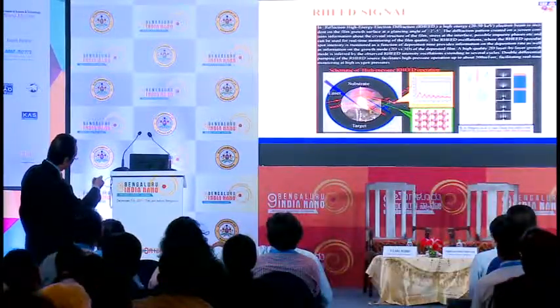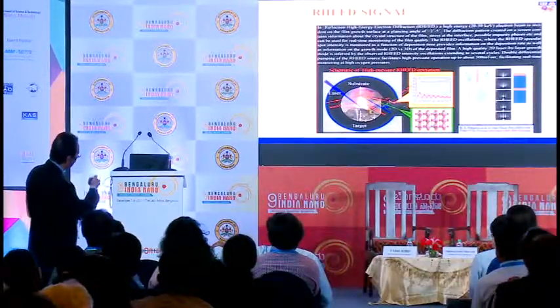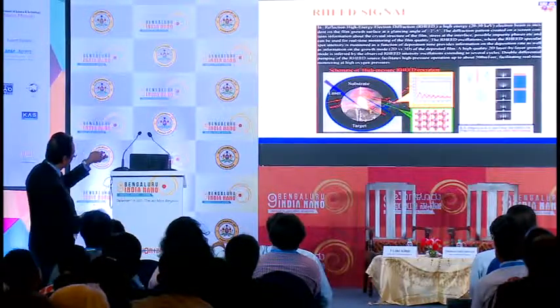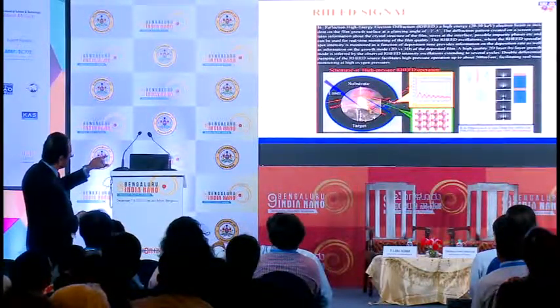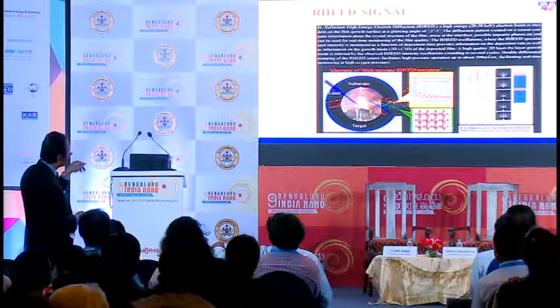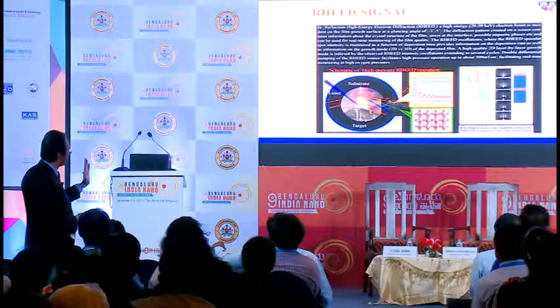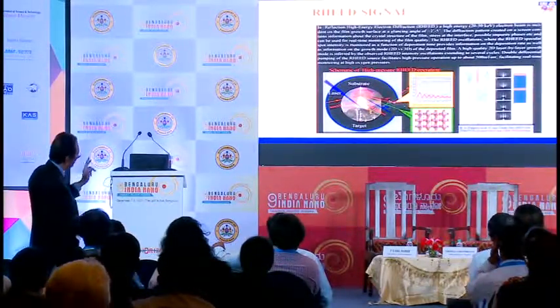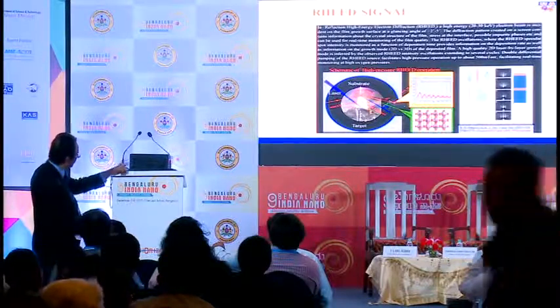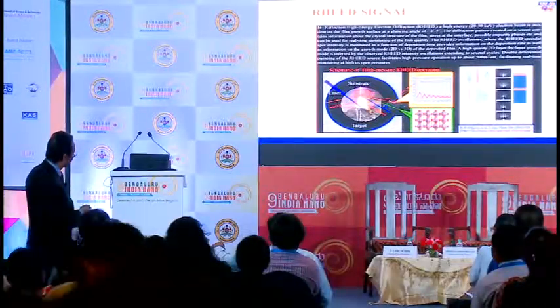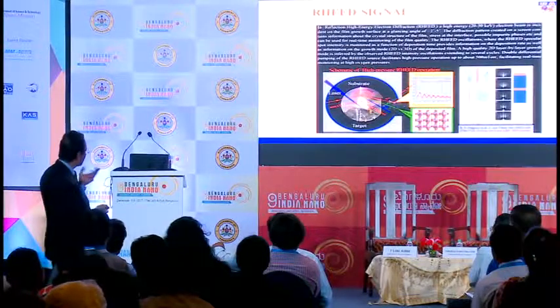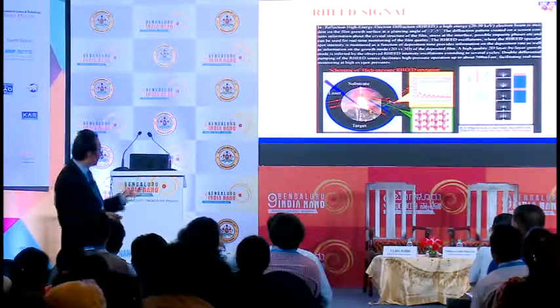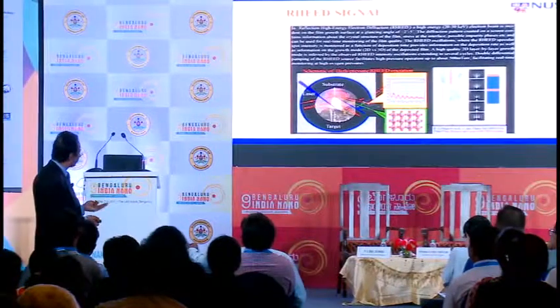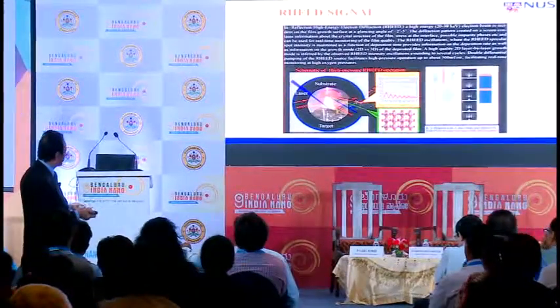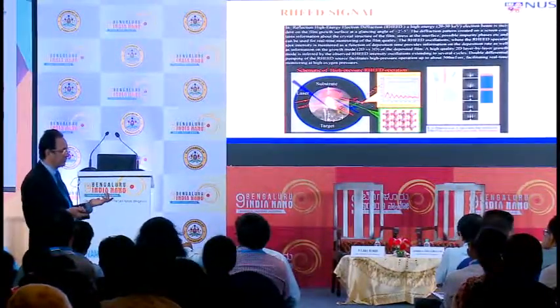And these oscillations represent one unit cell growth. So every unit cell growth corresponds to one peak, and therefore we can actually grow a film which is like a tenth of a monolayer in thickness, which is incredible accuracy. And you see the green diffraction patterns shown in the photograph in the middle, and that gives you the lattice constant. So we said, okay, we can get the lattice constant of the film, I can get the thickness of the film. How to get the composition of the film? That would be really incredible if I can do it in situ.